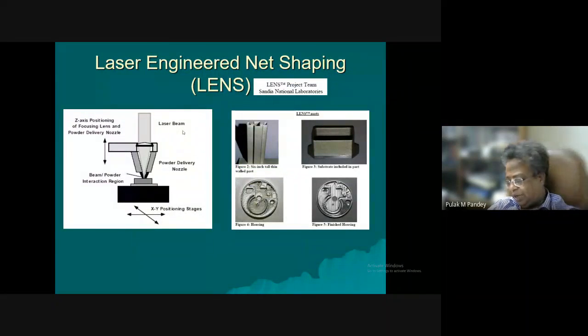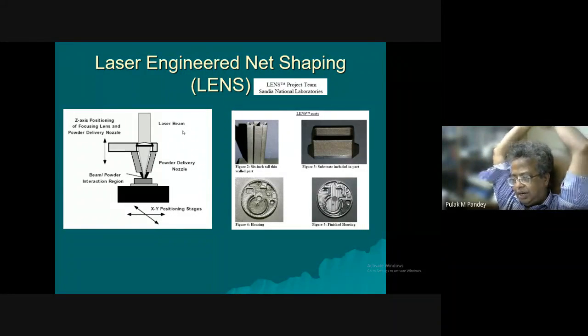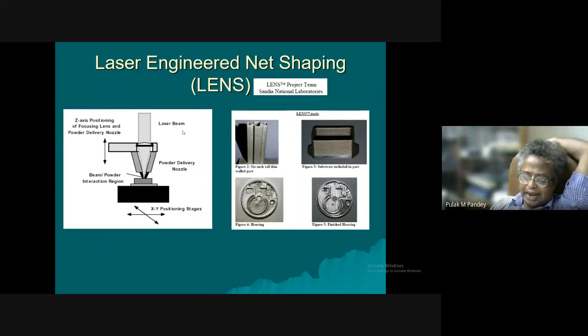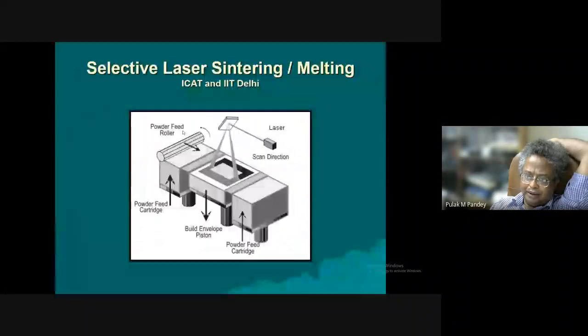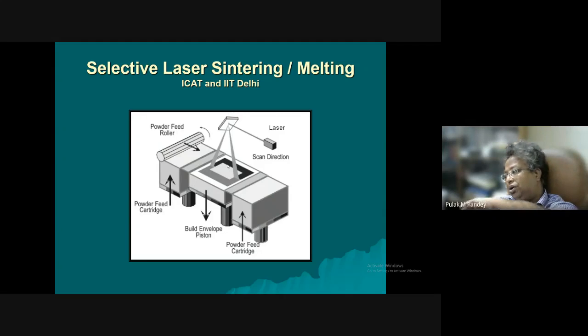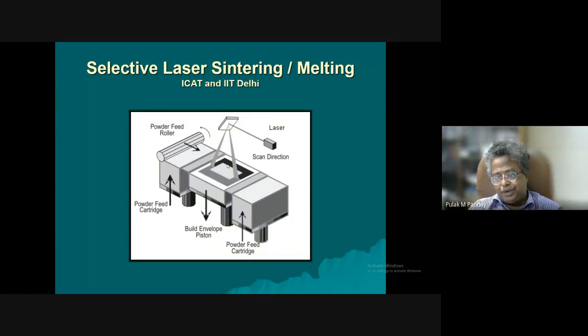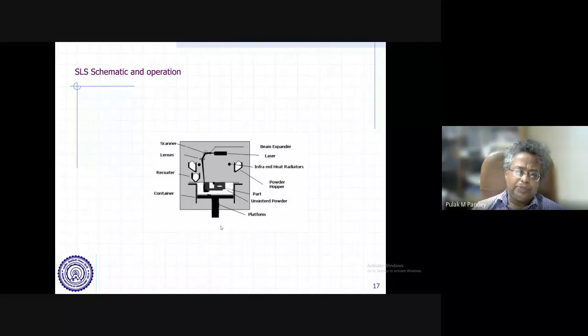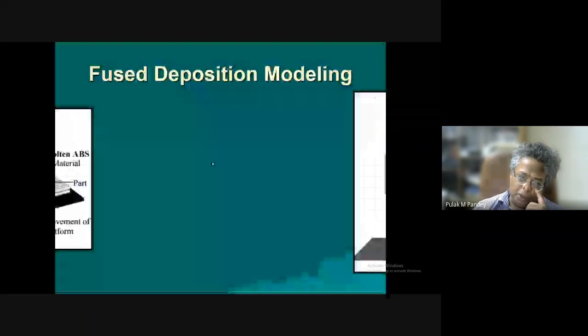Today we have advanced technology. There has been another concept of powder bed systems. The powder bed system is like the SLS system. We call it SLM when we talk about, say, metal. Here I can have polymer powder as well as metal powder. If I am using polymer powder, I cannot go much higher; the temperature requirement is up to 300 maximum. If I have to use metals, it will depend on the kind of metal we are using. In all SLM technologies, we are even going for superalloy deposition, so we go up to 1400 degrees Celsius, maybe more sometimes. You have to conduct this process in a proper environment, maybe an inert environment, so that the material does not react.